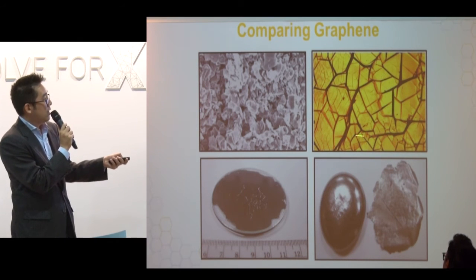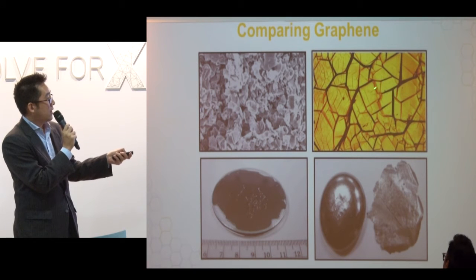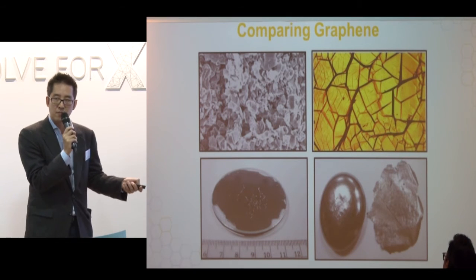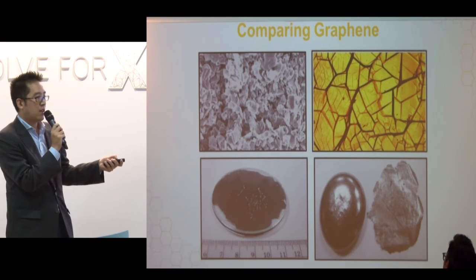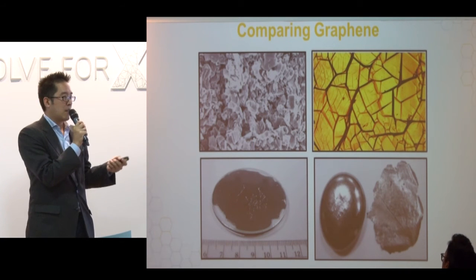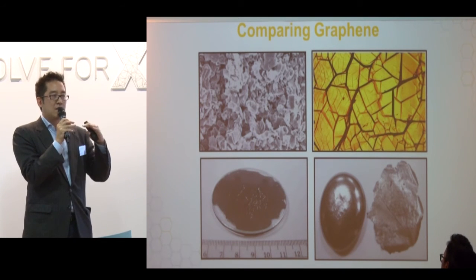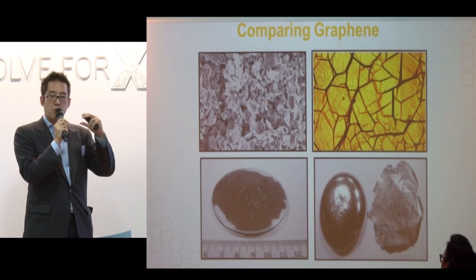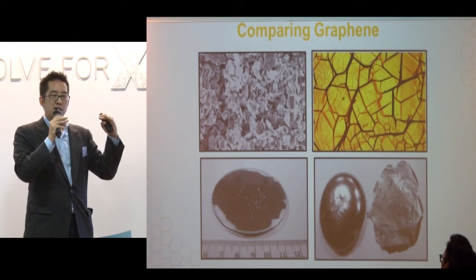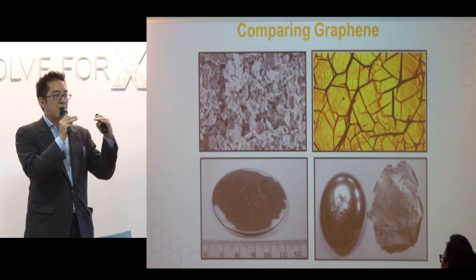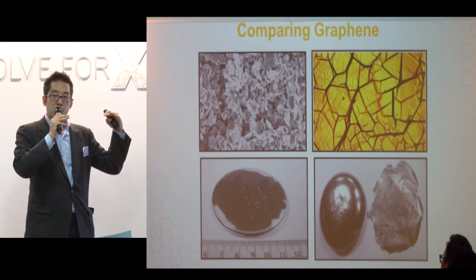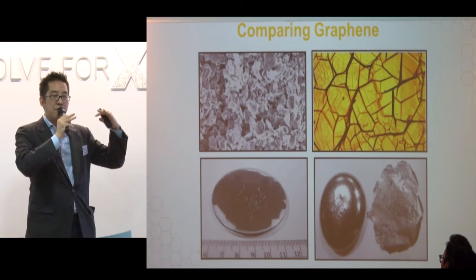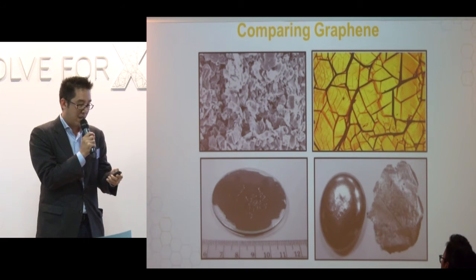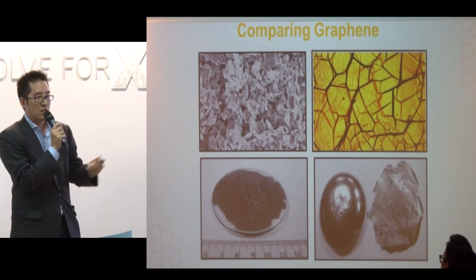This is an optical scan of our graphene. This is a single sheet of graphene. Why are there wrinkles in this? In our samples, the graphene sits on our metal layer. We cool down the metal layer, and there's a CTE mismatch, a thermal mismatch, so the metal shrinks a lot. The graphene on top folds like a fabric. But this is essentially one sheet of graphene.